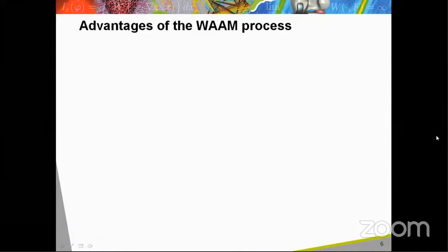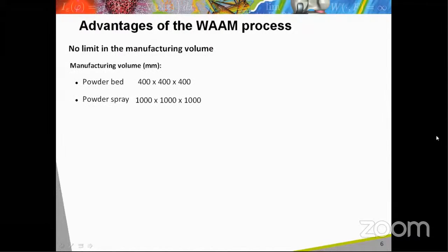In a general way, the WAAM process does not allow the same precision shapes of the manufacturing components as the powder bed technologies. However, it presents some advantages compared to the other additive manufacturing processes. First, there is no technical limit to the size of the manufactured samples because there is no manufacturing chamber with it. For comparison, the powder bed technologies are limited to the manufacture of components not exceeding about 400 mm size, and the spray technologies are limited to component size of about 1 meter long.